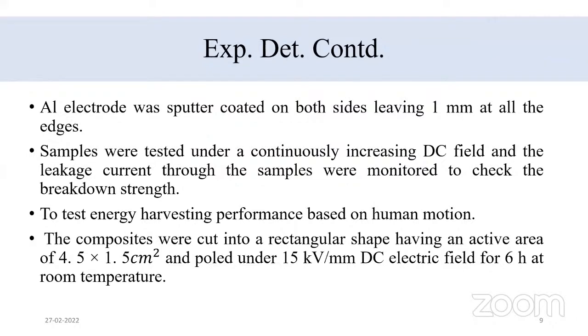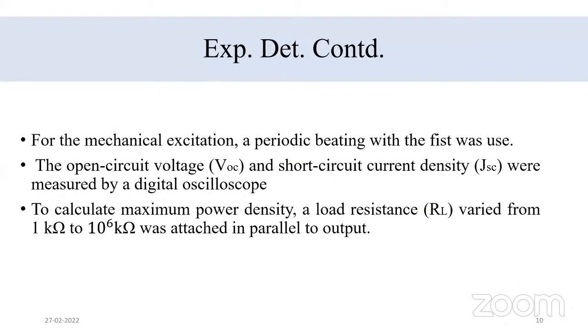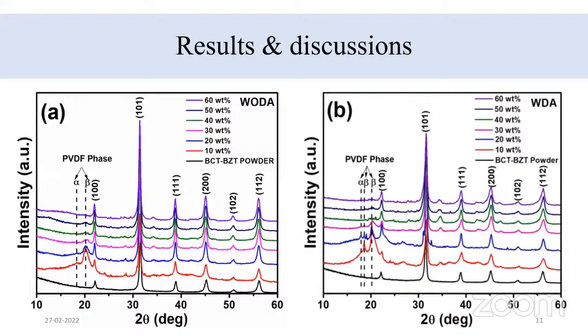Yes, sir. So the device was formed in a rectangular shape and poled under 15 kilovolt per mm for 6 hours. For mechanical excitation, periodic beating was used. After that, there is the XRD analysis of the samples prepared. As we can see, there are two, without dopamine added and with dopamine added. After the addition of dopamine, we can see two beta peaks. So beta phase increases by adding filler and dopamine.